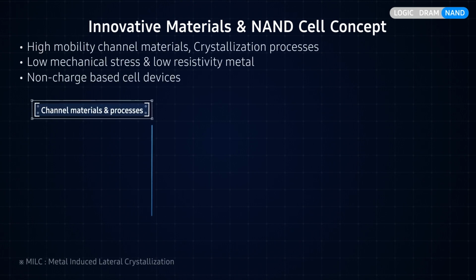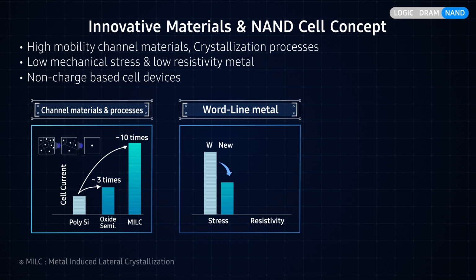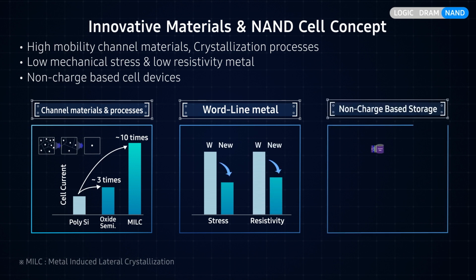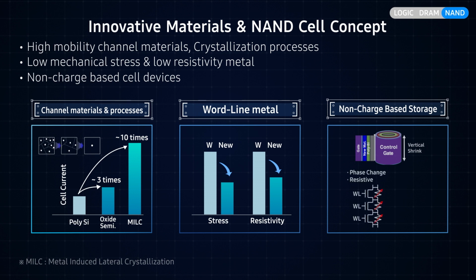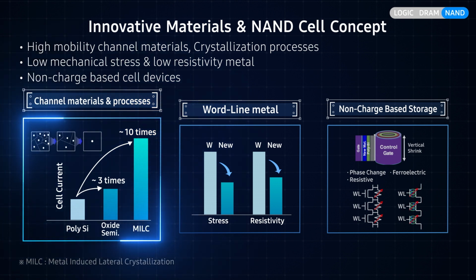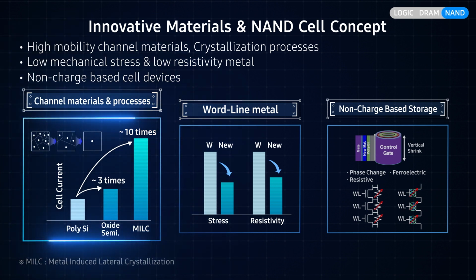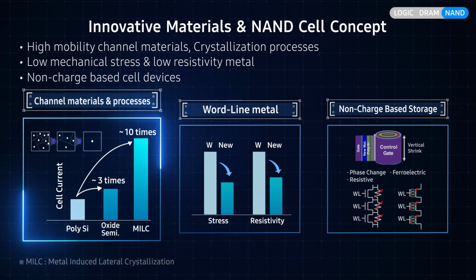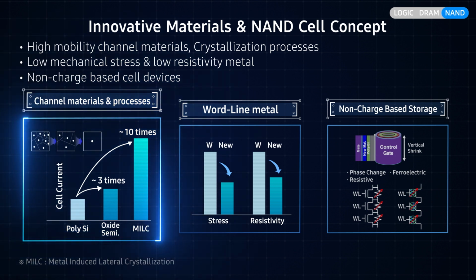We can mitigate these pressing challenges from the perspective of novel process and materials to tackle the issue of the low cell current. Probably we'll have two approaches. First, grain engineering. With recrystallization processes such as MILC, meaning metal-induced lateral crystallization, we can increase the grain size of channel polysilicon, thus achieve significant mobility enhancement. Second, novel oxide semiconductor channel materials, which have a higher mobility than conventional polysilicon channel. However, this comes with the challenge of controlling the memory window and ensuring reliability.